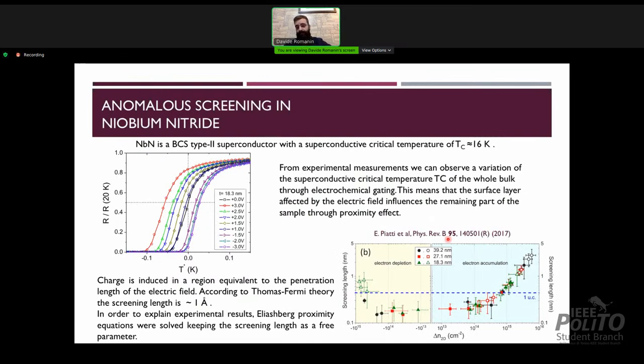As a next case study, I would like to discuss niobium nitride, which is a conventional superconductor with a bulk critical temperature of 16 Kelvin. Now, what we can see is that if we dope the system via field effect, as discussed before, we can achieve reversible shifts of the critical temperature. Indeed, we have suppression or enhancement of the critical temperature depending on whether we dope the system with electrons or holes.